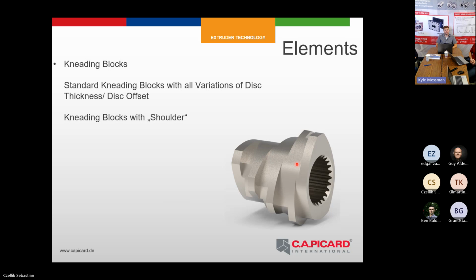So we also have kneading blocks which are customized. Here's an example of a kneading block with so-called shoulders. The modification here is you have a standard kneading block, but each kneading block, each kneading disc, has a cutout of about 50%. You can see it here or here. We are doing this because some customers have a very sensitive product where you don't need to put so much energy into the kneading zone or melting zone. So this is maybe the solution to not overstress your product.